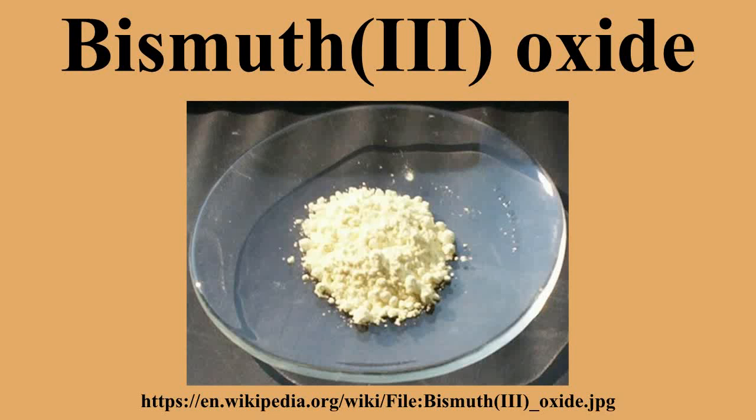Gatow and Schroeder rejected this model, preferring to describe each oxygen site in the unit cell as having 75% occupancy. In other words, the 6 oxygen atoms are randomly distributed over the 8 possible oxygen sites in the unit cell. Currently, most experts seem to favor the latter description, as a completely disordered oxygen sublattice accounts for the high conductivity in a better way. Willis used neutron diffraction to study the fluorite system.